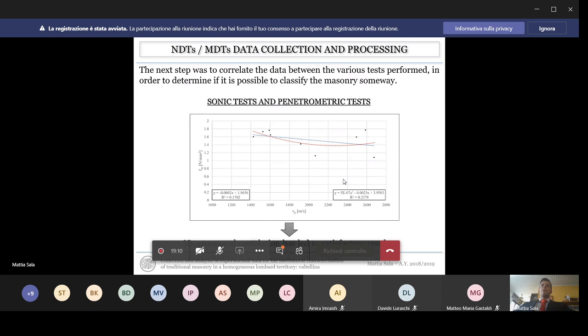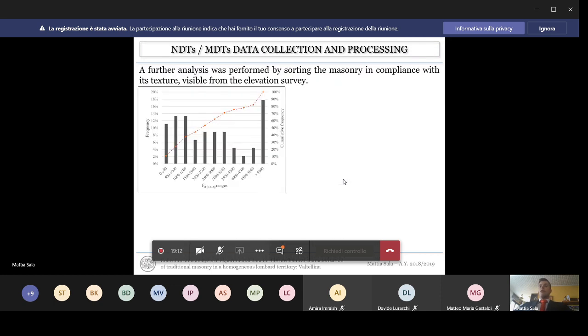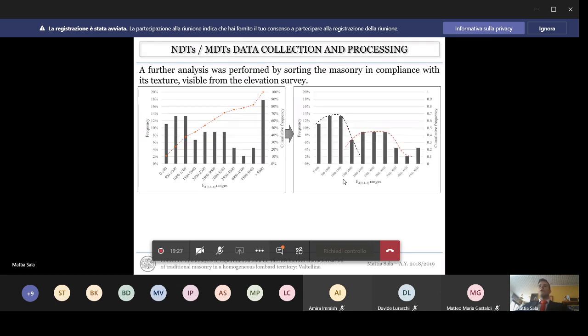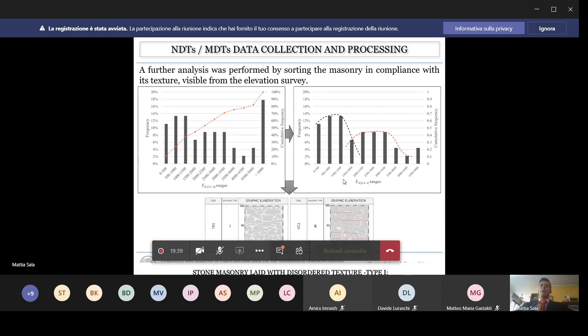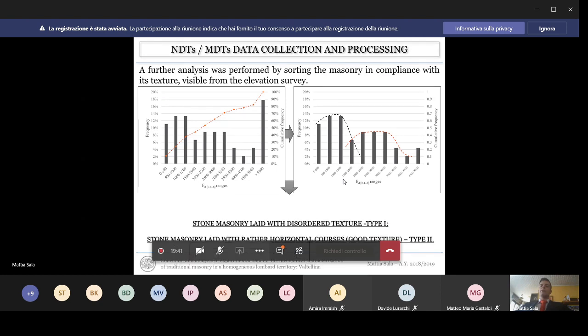The next step was to plot the graph of frequency of the deformability modules, and we see that there are a lot of values higher than 5,000 Newton per square millimeter, which are really stiff masonries and considered anomalous. Removing them from the data set, a sort of classification of the masonries according to the deformability modules is already visible. According to this hint, I performed a division of the masonries according to the texture into two typologies. Type 1, masonry with disordered texture, and type 2, masonry with rather horizontal courses.